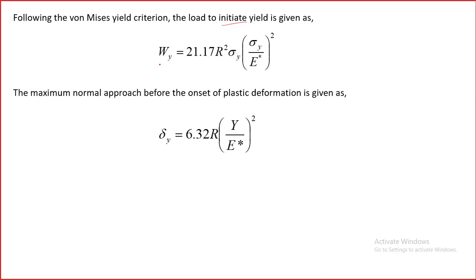So when the yielding initiates just in the subsurface, this gives us the load at yielding, which is given by this equation. Here you can see that this ratio is very important. This ratio tells us that in order to have a large load for yielding, this should be large. And this will be large if sigma y is large and if E star is small. So this ratio decides at what load the yielding will happen.